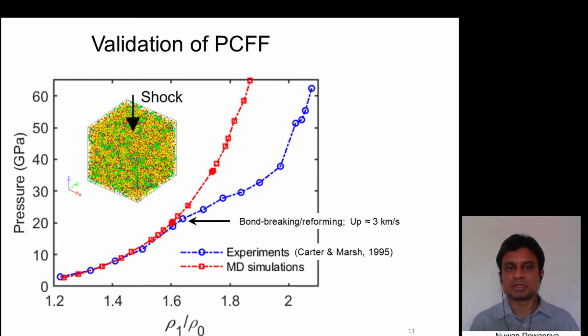Experimental results show that cross bonding of polymer chains occurs when the shock pressure is approximately 20 gigapascal and the corresponding particle velocity is closer to 3 kilometers per second. PCFF is a non-reactive force field. In other words, PCFF cannot model bond breaking or reformation, and therefore it follows the same path. Based on this investigation, we limited our highest impact speed to 3 kilometers per second.